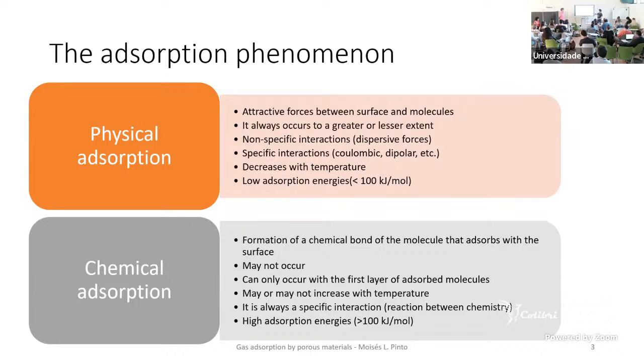So it only occurs at the first layer of the adsorbed molecules. So if it is a reaction, the first layer reacts to the surface, and the second and third layer of molecules that are left to the surface don't have more groups to react, okay? It may or may not increase with temperature, so it depends on the nature of the reaction you have. You know, there are reactions that are favored with temperature, and there are reactions that are unfavored with temperature. And it is always a very specific interaction. It's a reaction. It's chemistry, okay? And adsorption energies usually are above 100 kilojoules per mole. Again, I stress, these values are rough estimations.